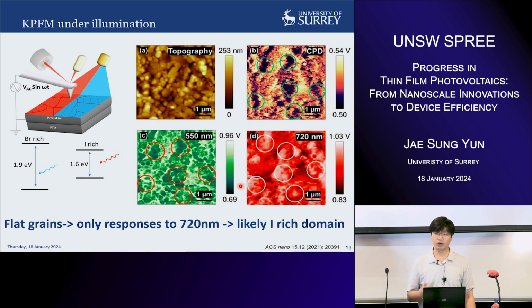So we measured KPFM under the illumination in order to see what these grains are in terms of their band gap nature. We can illuminate with two different wavelengths. As I explained earlier, we can have different band gaps in your materials for wide band gap perovskite. Under the light illumination, they will have a bromide-rich region and an iodine-rich region due to the phase segregation. So if you illuminate blue light, larger energy light, we can see more response in bromide-rich grains, and if you use around the red region, we can make the iodine-rich region more responsive to the KPFM signal.